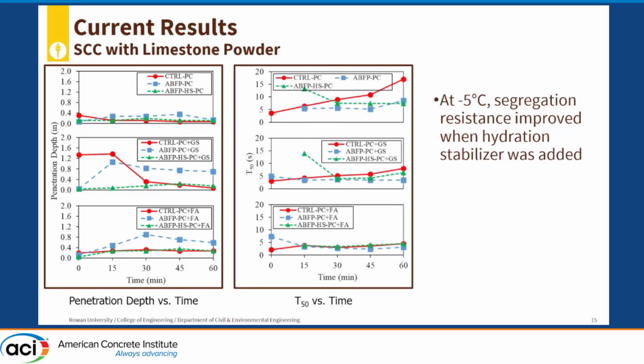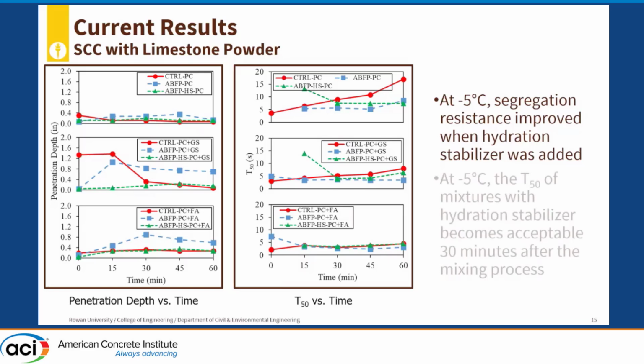This one is the T50 versus time. Our acceptable value for T50 is between 2 seconds and 10 seconds. So again, T50 is the time it takes for the spread diameter to reach 20 inches or 50 centimeters. We noticed that mixtures with ABFP only, without hydration stabilizer, have acceptable T50 values from 15 minutes to 60 minutes. But for the ones with hydration stabilizer, they needed 30 minutes after the mixing process to have an acceptable T50 value.